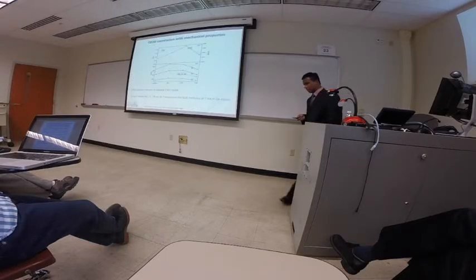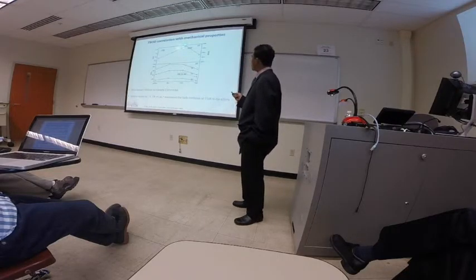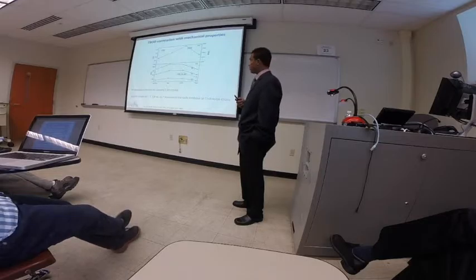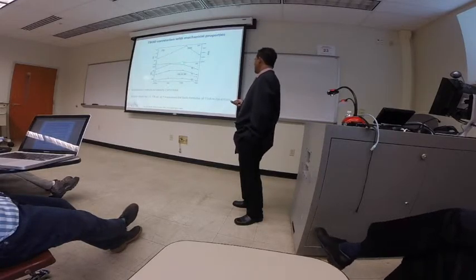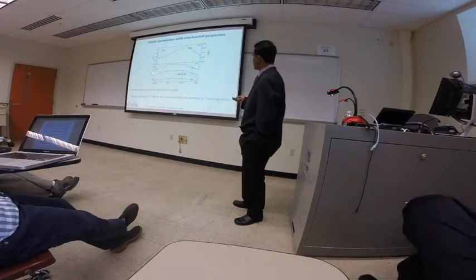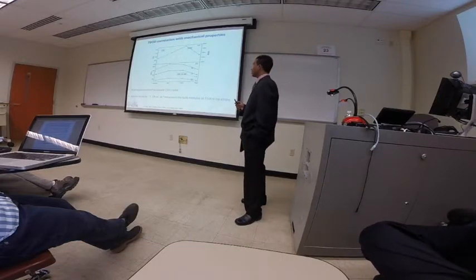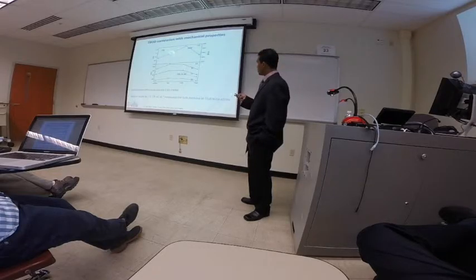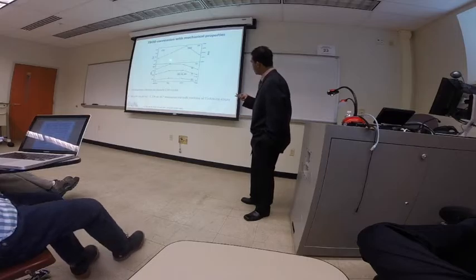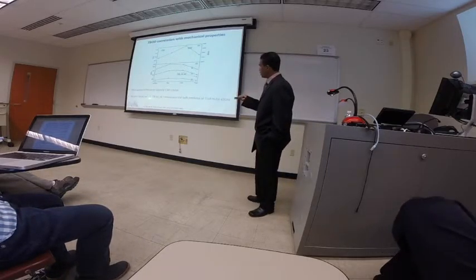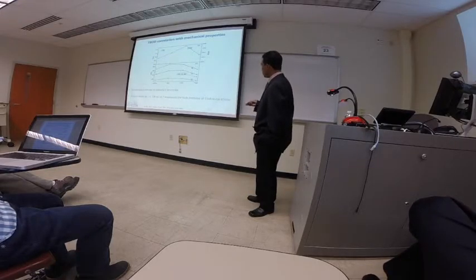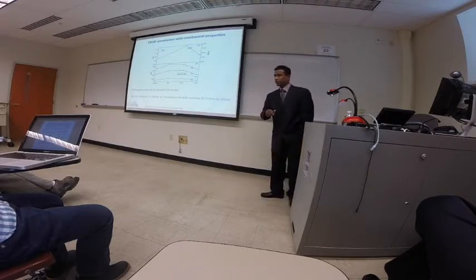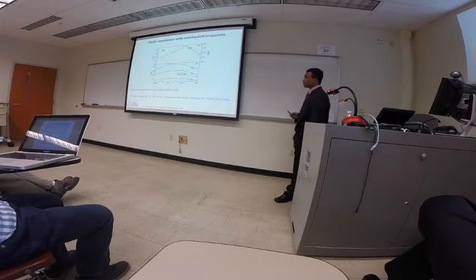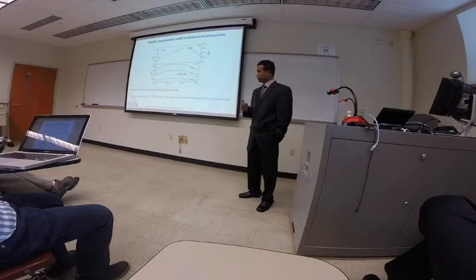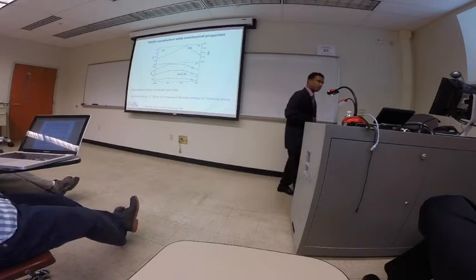So to test our hypothesis of how effective bond order density is, and to find the relation between that and the mechanical properties of the cement crystals, we made this plot. And you can see at first glance the trend of the mechanical properties seems to correlate fairly, well, I wouldn't say well, but it seems to correlate somehow with bond order density, as opposed to the traditional CaO/SiO2 ratio, which gives an inverse trend. And also the experimental study is close to our value, just to make it consistent. Experimentally measuring mechanical properties in cement crystals is extremely difficult, just because of the difficulty of synthesizing cement crystals.